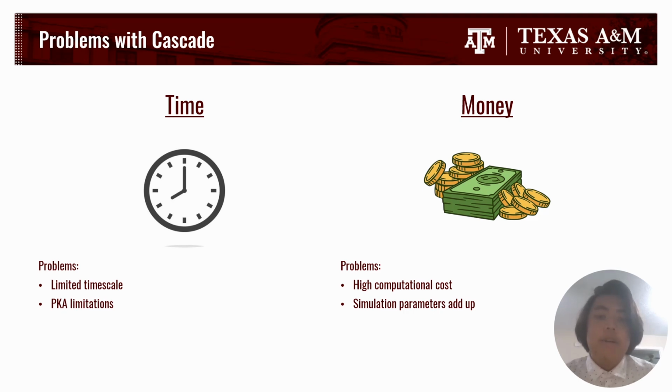This also only characterizes the first picoseconds of radiation, when radiation can happen over many, many years. The many cascades are expensive computationally and monetarily. For cascades to be meaningful, the simulation boxes have to be large, which means simulating hundreds of thousands to millions of atoms, which just means way more force calculations. Cascades also require system evolution, which takes even more time and computation. In terms of monetary cost, these cascades can consume a lot of CPU core hours, which can take thousands of service units through HPRC, and actual money if you're renting computation time.